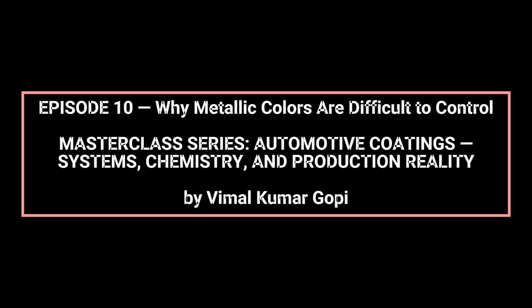At the process level, metallic base coats are extremely sensitive to spray parameters. Changes in atomization energy, spray distance, overlap, or gun angle alter droplet size distribution and impact velocity, which directly affect how flakes enter and spread within the wet film. Minor operator or robot deviations can produce measurable appearance shifts.